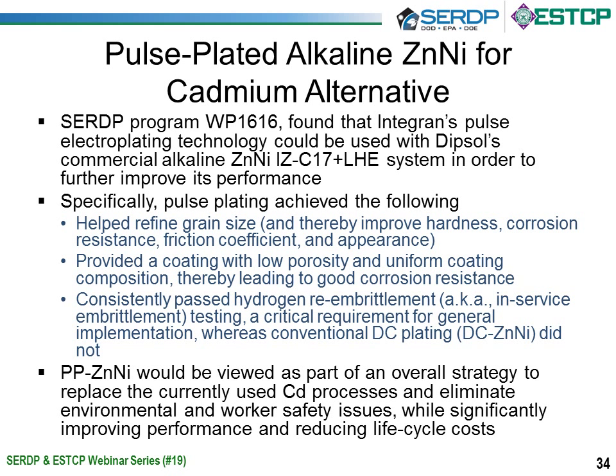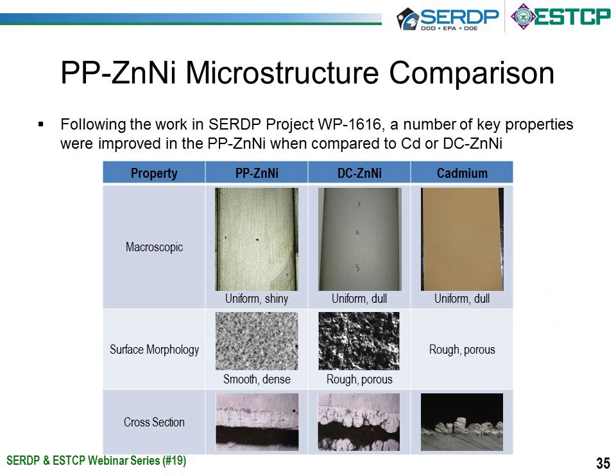Specifically, what we found is that pulse plating was able to help refine the grain size, which improved the corrosion, hardness, coefficient of friction, and the appearance as well. It provided a coating with low porosity and uniform composition, thereby leading to good corrosion resistance. And it consistently passed the hydrogen re-embrittlement test, also known as the in-service embrittlement test, which is a critical requirement when plating on high-strength steels. Whereas in our testing, we found that the conventional DC plating did not consistently pass this, which I'll go into in a little more detail in the following slide.